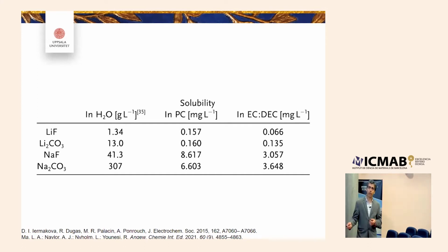There's also a clear trend that if you compare on the same solvent, sodium species versus lithium species, we see much higher solubility of sodium species. This is another indication that the solubility of these components, if they are in the SEI, is a challenge. This might also indicate that we are more dependent on forming organic species in the SEI of sodium compared to the SEI of lithium-ion batteries, because we want to reduce the solubility.